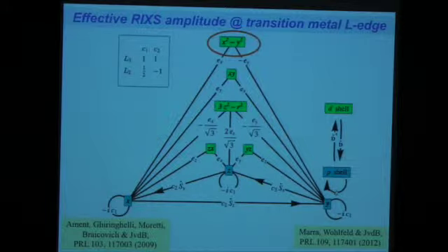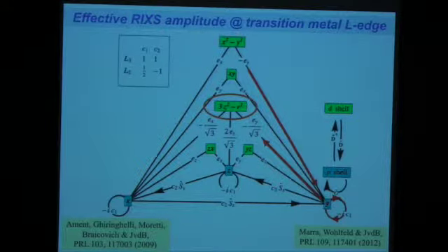For instance, I start with a hole in the x squared minus y squared orbital. Now the first move is absorbing a photon, for instance with polarization EY. So start with polarization Y, I end up in a P shell, in a P core hole with PY character. Or you can say, I have a hole in x squared minus y squared, the hole is demoted into the core by the absorption. Now I make a second move. For instance, the second move can be to do the circle, which means picking up a constant, C1. And now the third move is emission, and if I emit a photon with polarization Y, I pick up another constant, and I end up in a 3z squared minus r squared orbital. So you see, I can get from x squared minus y squared to 3z squared minus r squared if I know the polarizations and I know these numbers that I pick up there. And this is true for any DD excitation in my system.